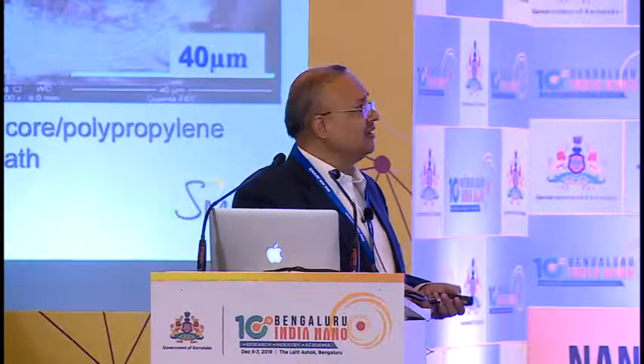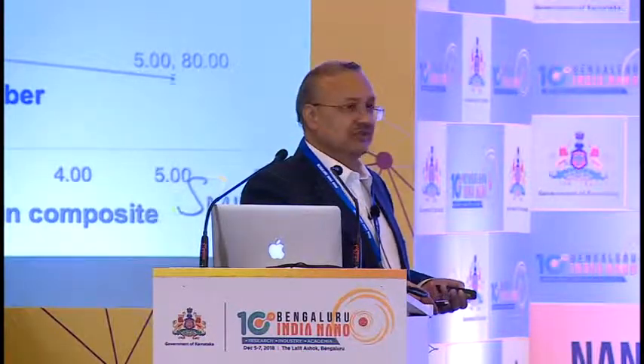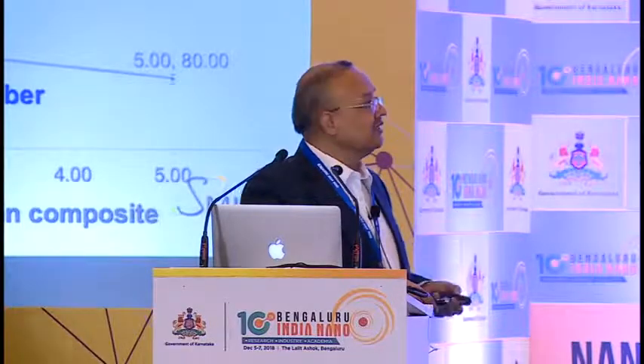We did a bi-component spinning. It's again a very specialized kind of spinning process. And we created a fiber which had a sheath and a core. Core had conducting material, and the sheath was insulating. Then we dissolved the sheath at one end of the fiber. So obviously the conducting surface hopefully has come out. And then we took it as a wire. And what we see is if you do not remove the sheath, it is absolutely insulating. But if we remove that sheath and come to the core, the conductivity is almost 7 orders of magnitude better.